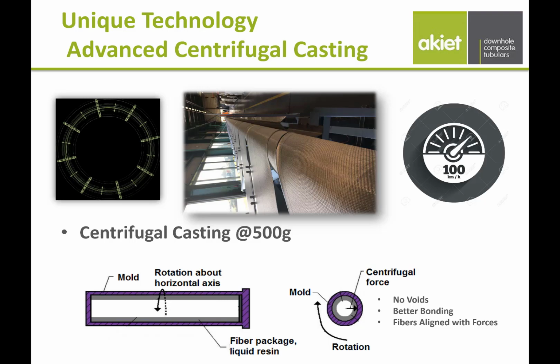And then the epoxy is inserted in the mold. The epoxy, of course, flies to the outside under centrifugal forces and penetrates all the way through the glass. And because of the spectacular amount of G forces, you find that all moisture and all air is being driven out of the structure and goes to the inside of the mold. And after hardening, what we're left with is a pipe body that is totally free of voids, and the glass sits exactly in that orientation where we've engineered it to be.